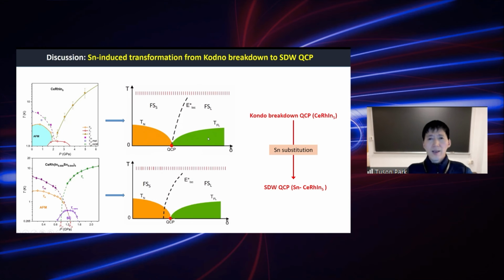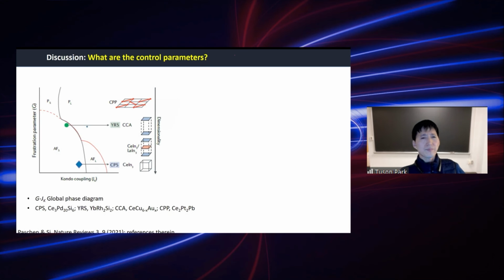So we can conjecture that the separation or the appearance of a new critical point inside a phase may be due to a transformation of the Kondo breakdown type QCP in the pure compound to a spin density wave type QCP by tin substitution. So then the question is, how is that possible? We just do tin doping, only 4.4%, a minimal doping.